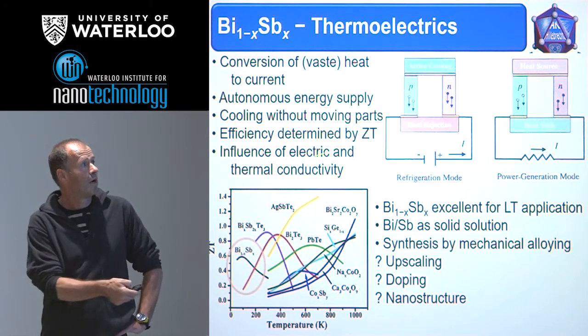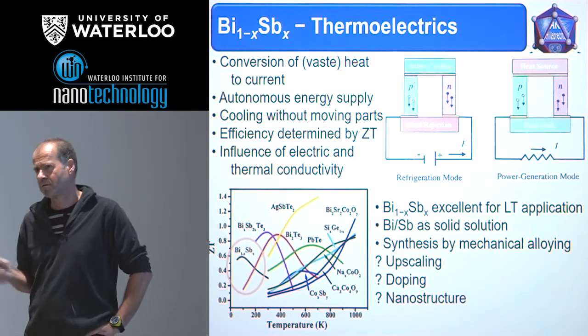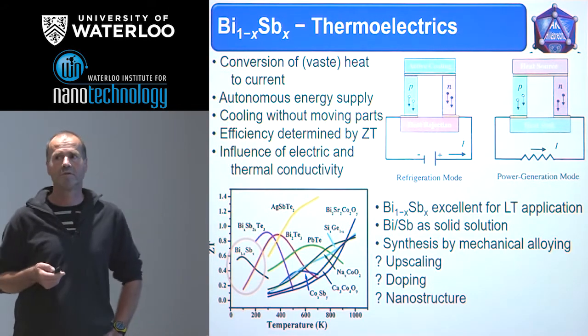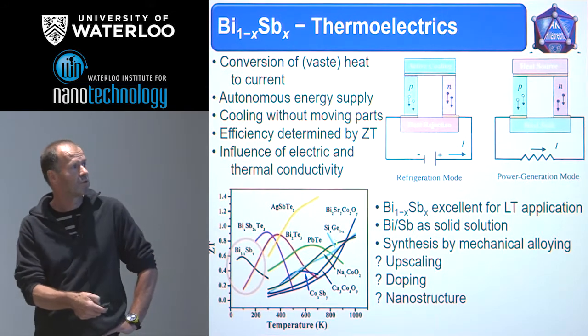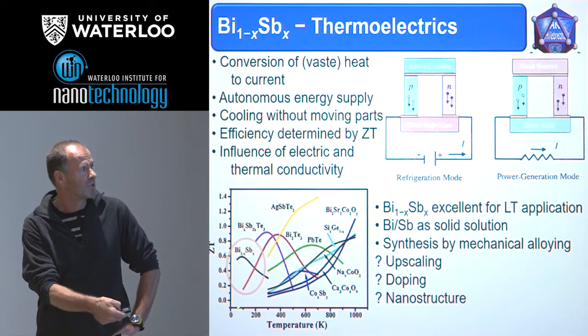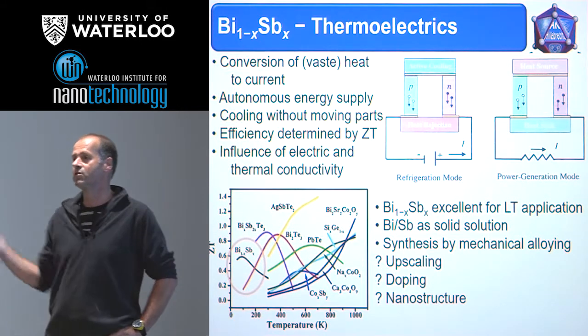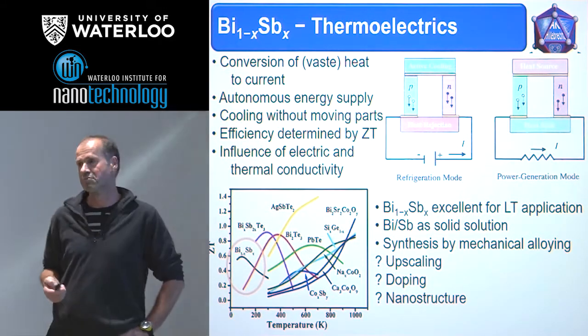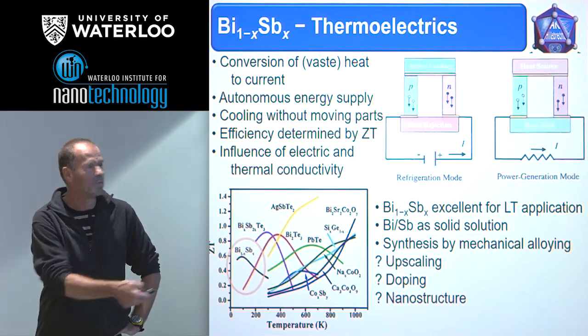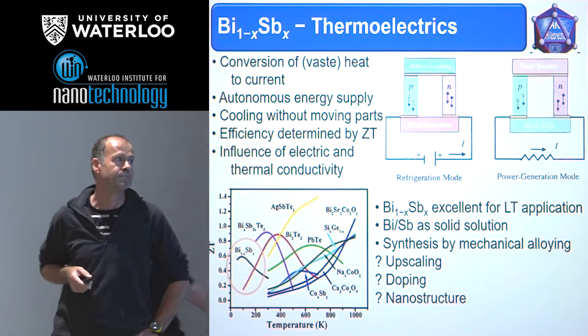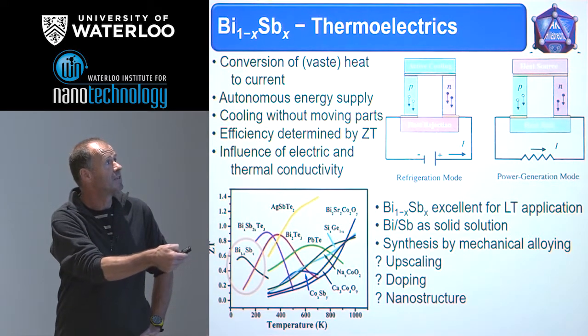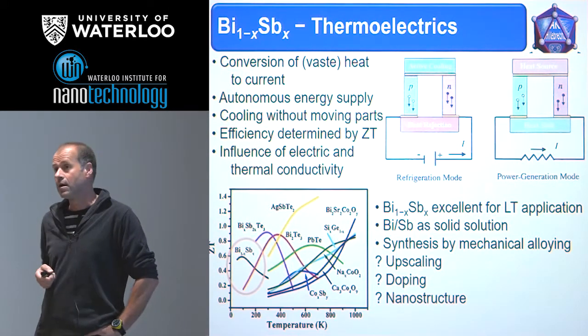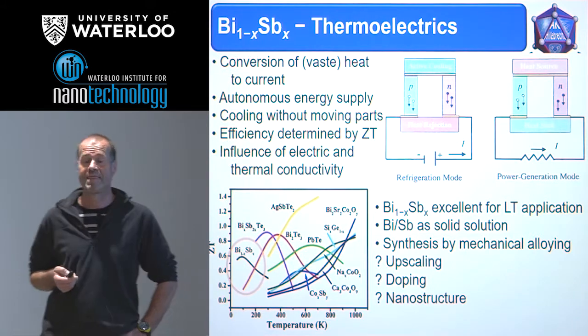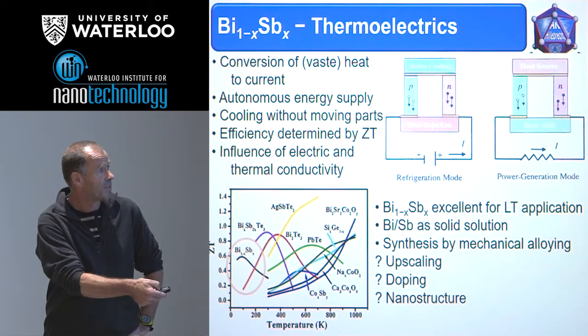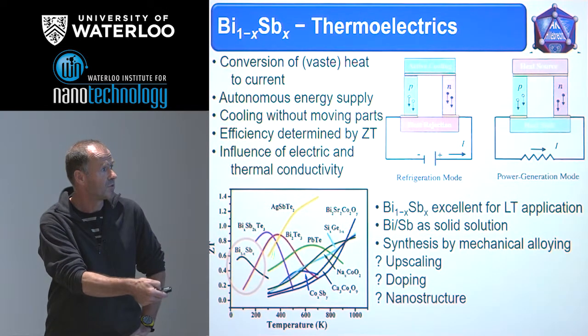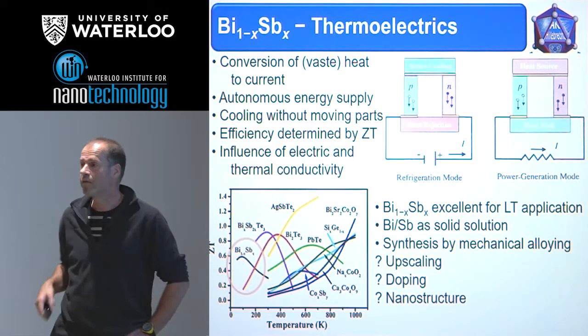As you all know, electric and thermal conductivity are not independent, they are coupled by diverse physical laws. And one of the important curves is this one. That means the so-called ZT value, that's the holy grail of thermoelectrics. We should have a value of about 1, but don't care too much about it. Why did we start with these systems? We had a project on bismuth telluride, which is this representative here, and you see that around room temperature, bismuth telluride is one of the best materials.